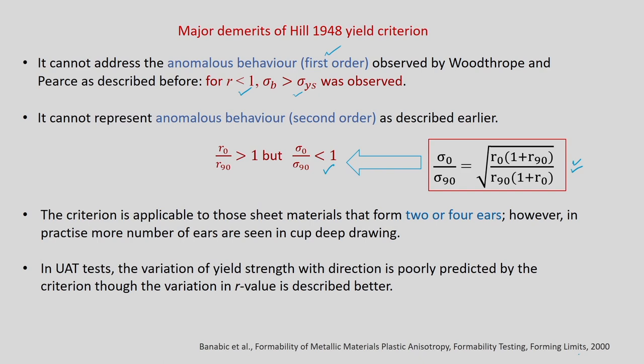Moreover, generally the criterion is applicable to sheet material which has only 2 or 4 ears during deep drawing. So, like we said, in cup deep drawing, earing is formed. Only 2 or 4 ears will be formed, so the deep drawing behavior can be predicted accurately using this yield function which has 2 or 4 ears during deformation. But practically there can be more ears that form, which cannot be addressed